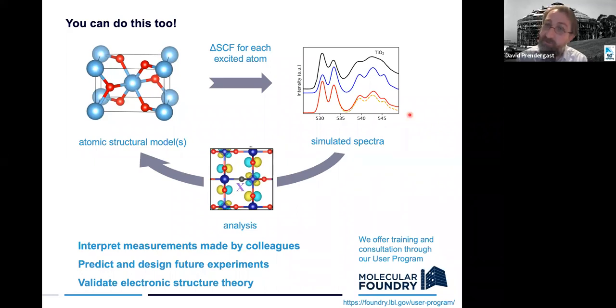And you get to a point where you begin to realize, yes, there are some mistakes in the literature. And there's even some surprises. So let's say something is labeled as an oxide, but when you do the simulation, you find, nope, it doesn't look anything like that. And you find out that actually the experiment had some impurities on its surface. And actually it was a carbonate, not an oxide.